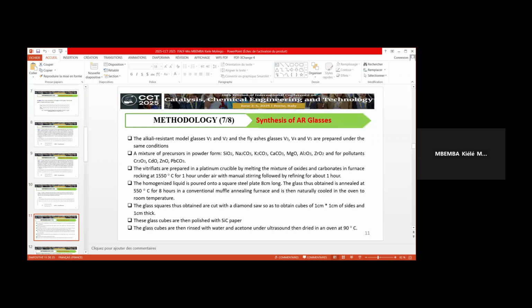So all the glasses were synthesized under the same conditions. We first mixed precursor oxides and pollutant oxides. And the mixture was put in a furnace at 1,550 degrees Celsius for 1 hour. And when the glasses were obtained, they were annealed at 550 degrees Celsius for 8 hours.